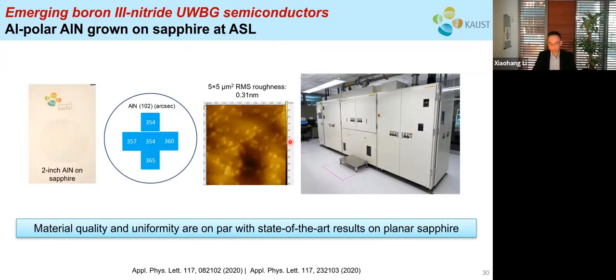So with that knowledge in mind, we have continued to optimize the aluminum polar aluminum nitride grown on sapphire by our MOCVD at KAUST. And currently, this is the X-ray analysis indicating the material quality. And here is the AFM image indicating the surface roughness. So both material quality and surface roughness are on par with the state-of-the-art results of direct growth of aluminum nitride on planar sapphire. But you can also see we still have a lot of dislocations represented by those darker dots on the surface. And that's something we still have to work on in the future.